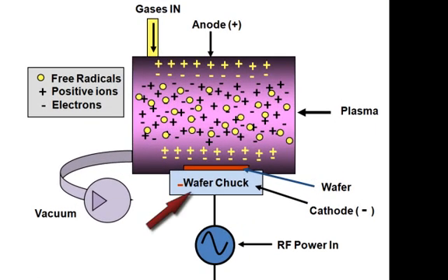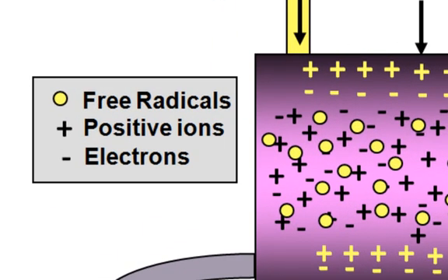Wafers are placed on a negatively grounded holder in a vacuum chamber. A gas is introduced into the low-pressure chamber, which is usually less than 50 millitorr, or down into the high vacuum region. RF power is applied to the chamber, and a plasma is struck. In the chamber, the gas molecules pass through the plasma and collide with high-energy electrons. The energy is transferred from the electrons to the gas etchant molecules. These collisions result in high-energy state positive ions as well as free radicals.